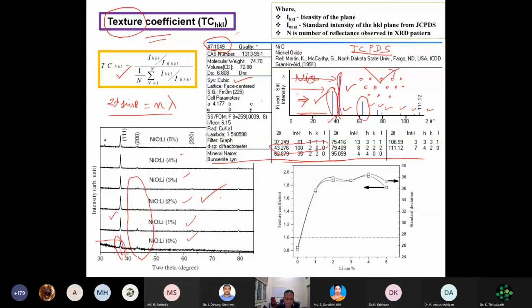What will happen here is, if I have a diffraction pattern, say for example, if I have particles sitting in all possible orientations, HKL planes, then when I do a diffraction pattern, this kind of pattern will come. But because of the growth procedure which is happening in this material, you will see that all the particles will not have a random orientation. They have some kind of preferred orientation in only one direction or two directions only. They may be sitting like this uniformly, and the thickness is very, very thin.